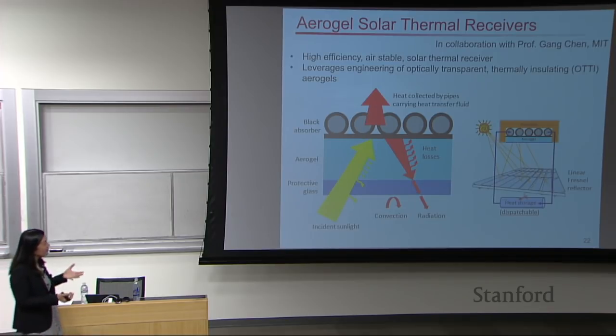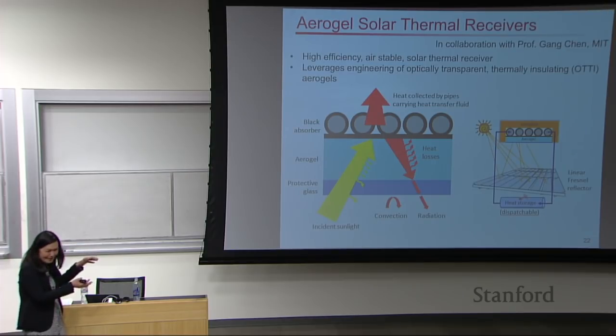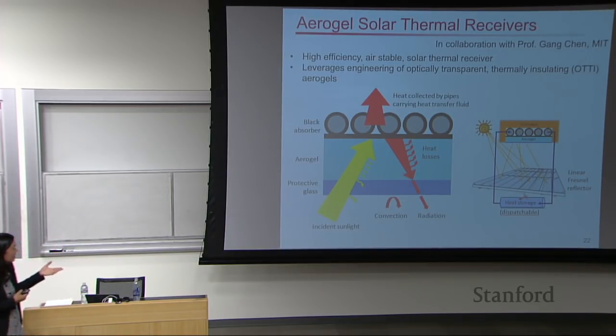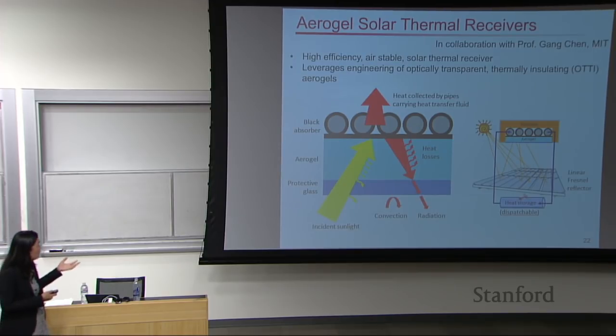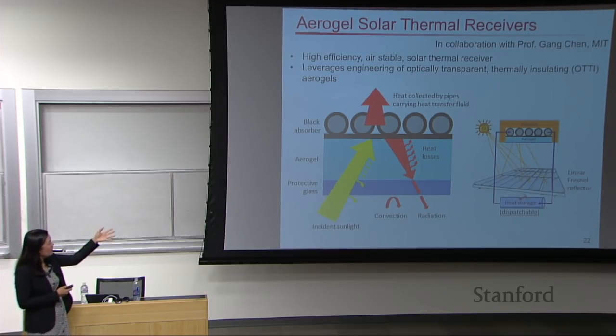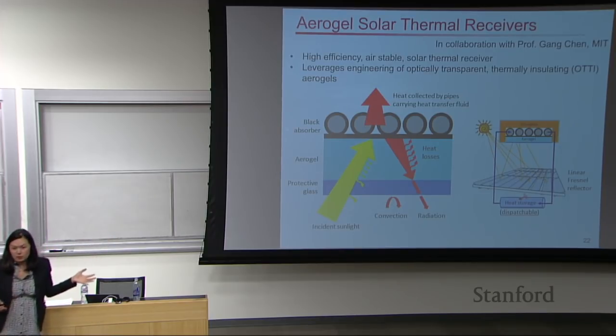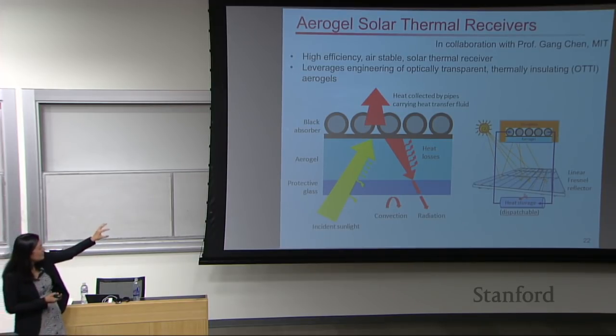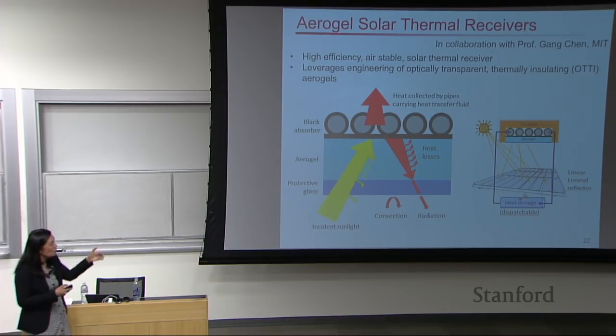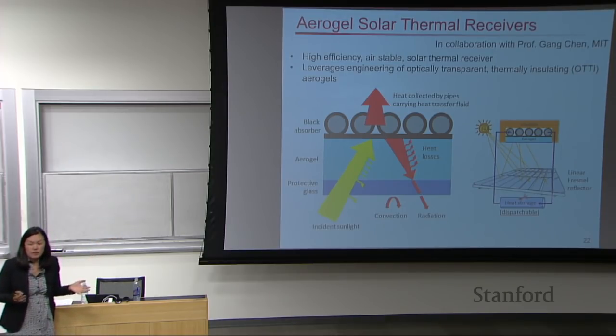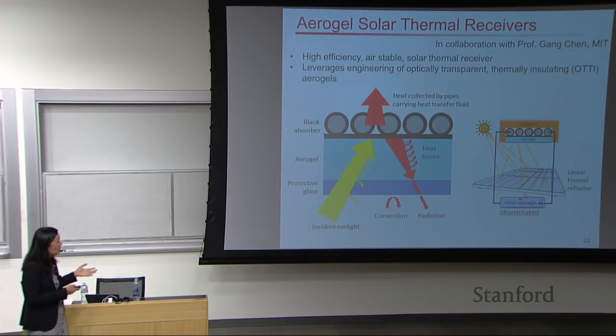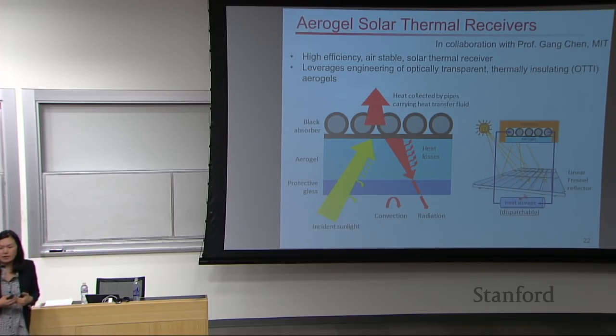So we're using these optically transparent, thermally insulating aerogels, such that effectively we're creating a greenhouse. Right? And in this way, we can trap the heat locally and heat up these tubes while minimizing the losses due to radiation and convection as well. And the opportunity is the fact that these aerogels also don't have to operate in vacuum, right? If we can, in fact, conceive this design. And so instead of using, say, a parabolic trough type configuration, we can move to linear Fresnel reflectors at lower concentrations, also facilitating potentially lower cost in this case.